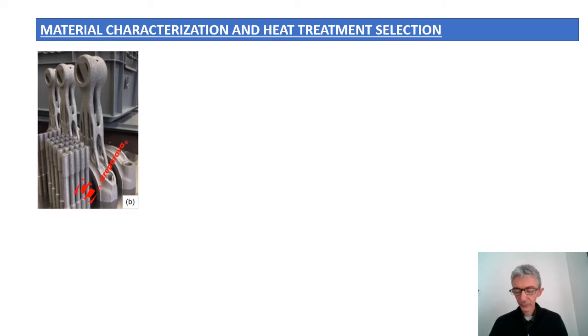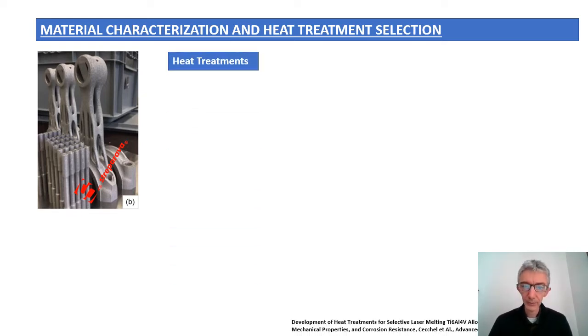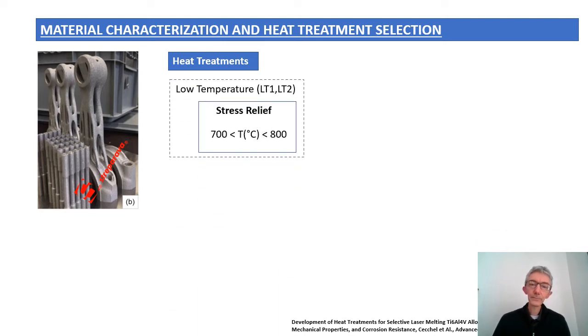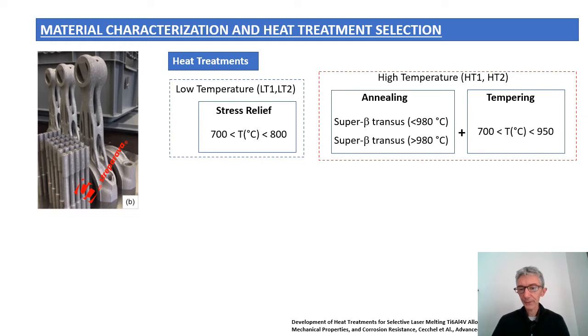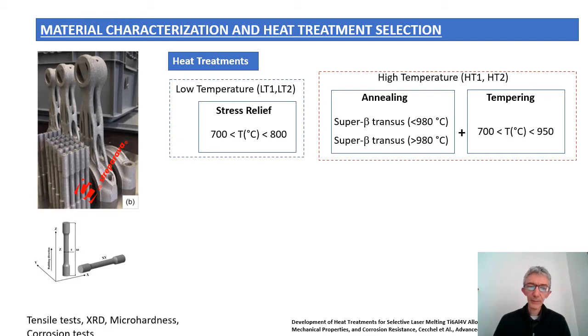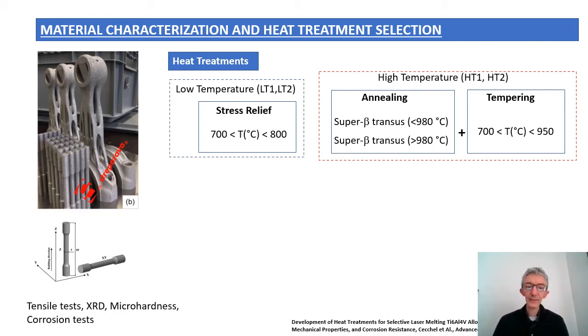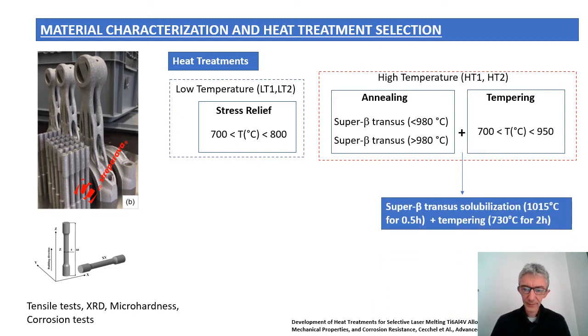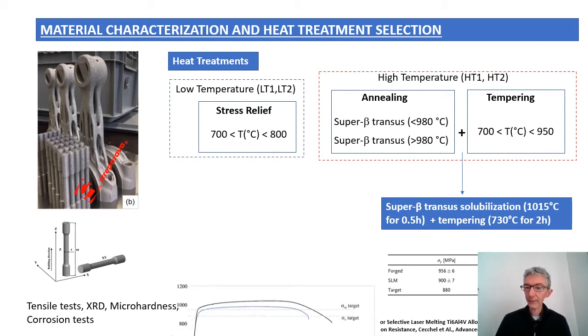The next phase of the research, after printing some prototypes and samples, was material characterization and heat treatment selection. This activity was carried out by our colleagues from Metallurgical, and in particular they compared different types of heat treatment, both at low and high temperature, and they considered different building directions and carried out tensile tests, XRD analysis for residual stresses, micro hardness, corrosion tests, and in the end they selected a super beta transus solution followed by tempering as the most promising heat treatment among those analyzed.